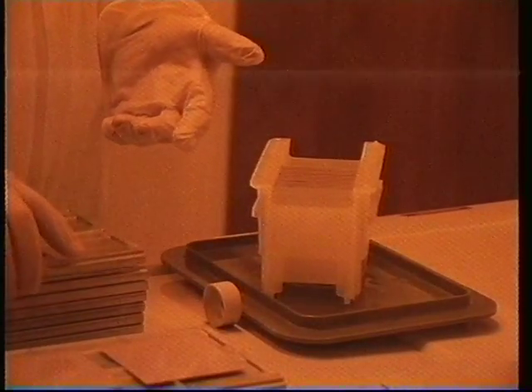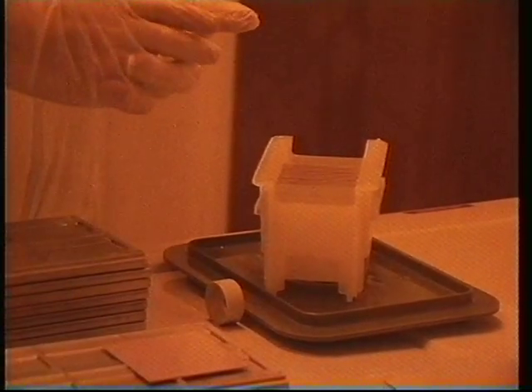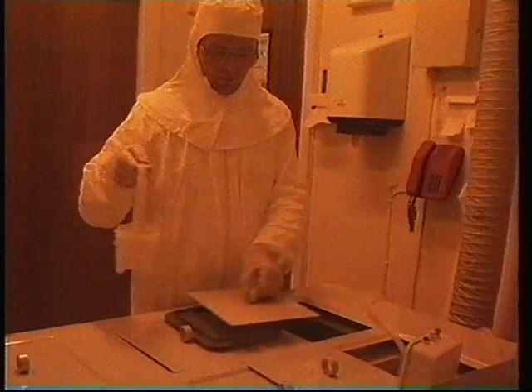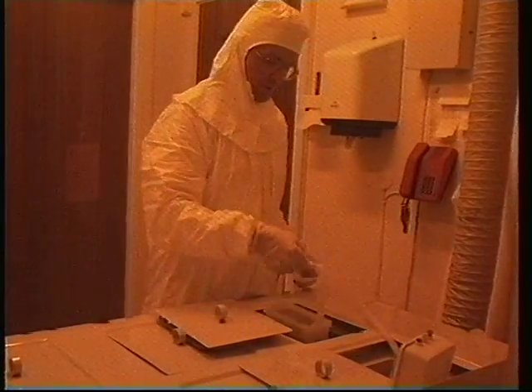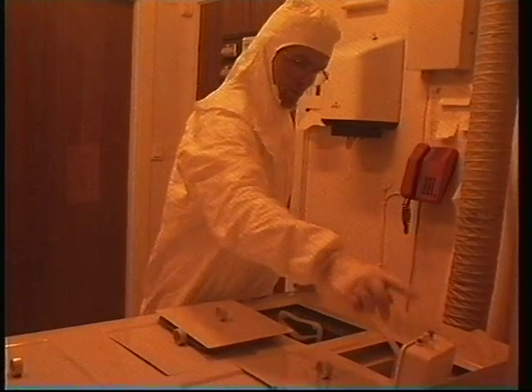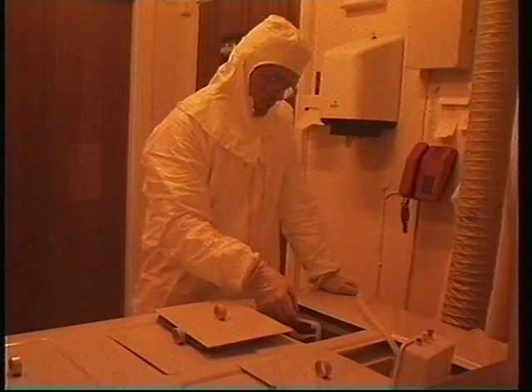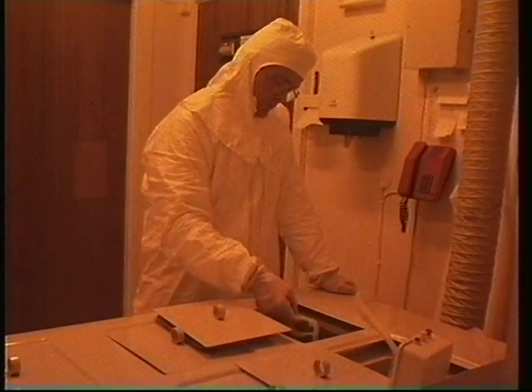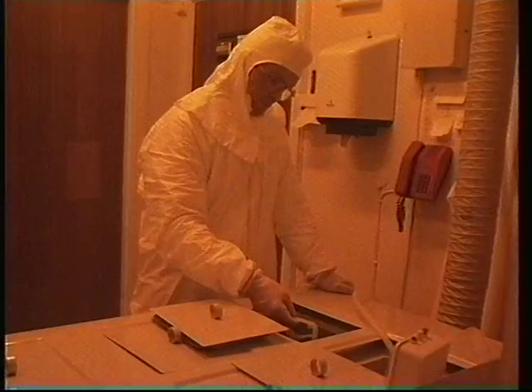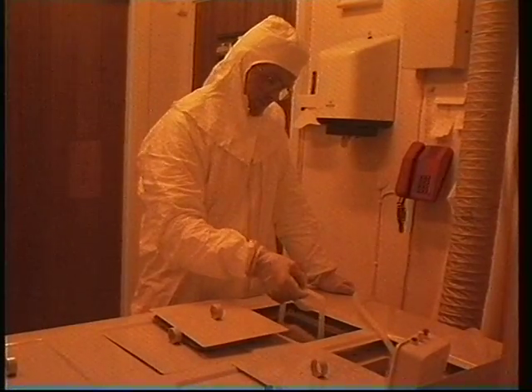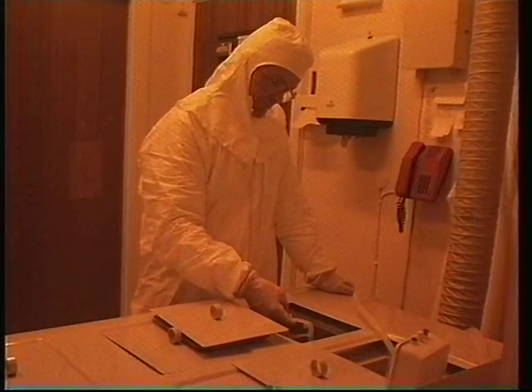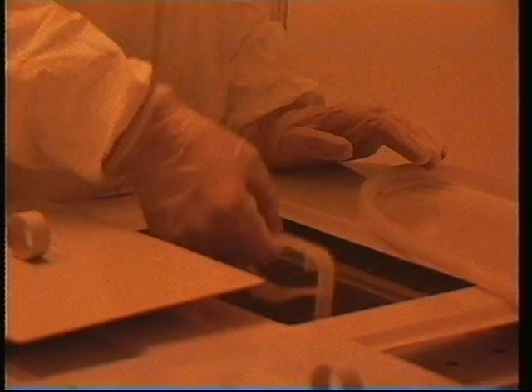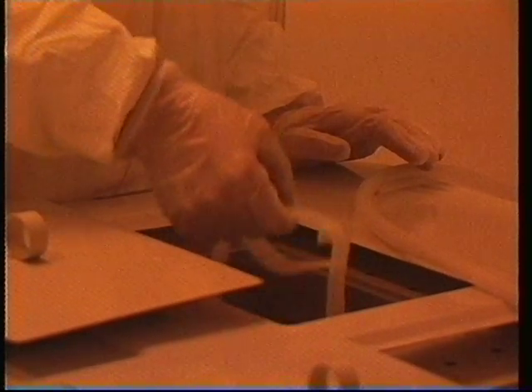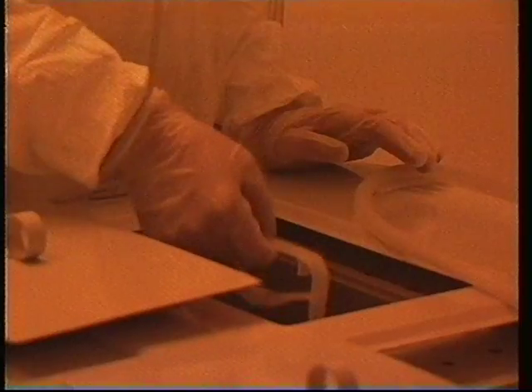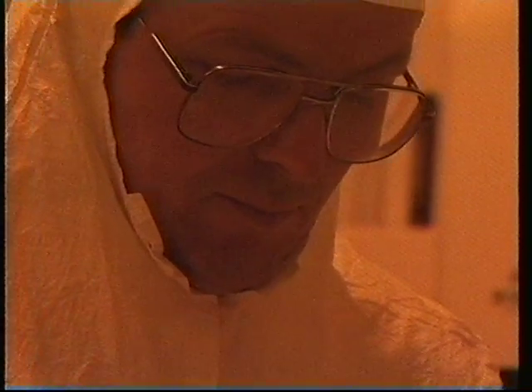Now, we are ready for the chemical etching of the gold metal layer. The first etching bath consists of a mixture of potassium iodide and iodine. This mixture dissolves gold, but not the protective photoresist, nor the titanium. The titanium is etched in a second bath, which contains hydrofluoric acid. Then the substrate is rinsed with water.